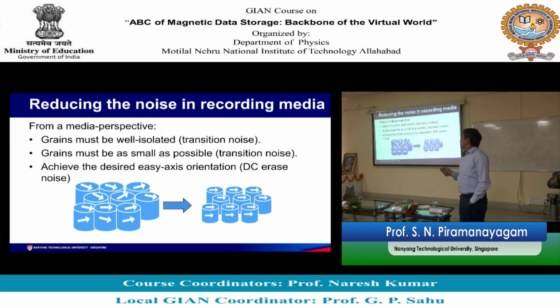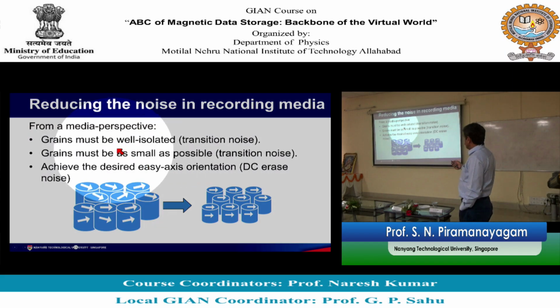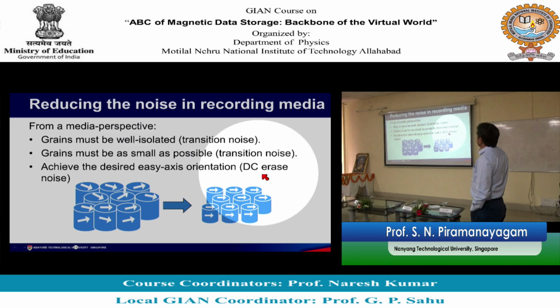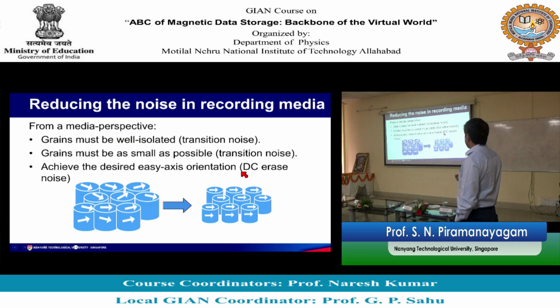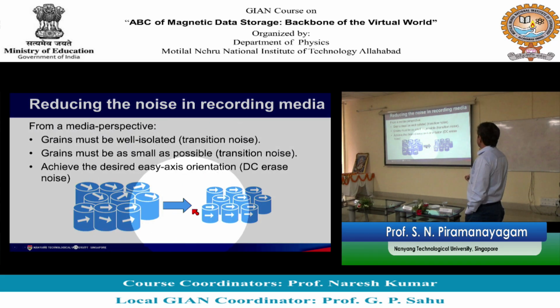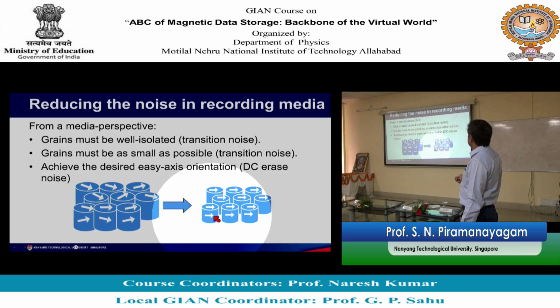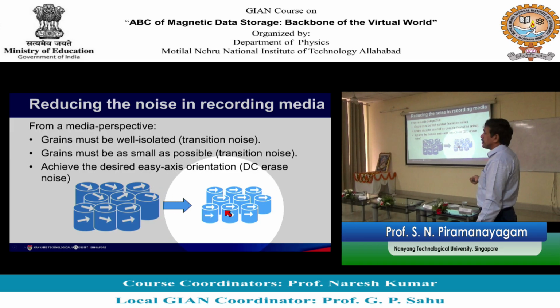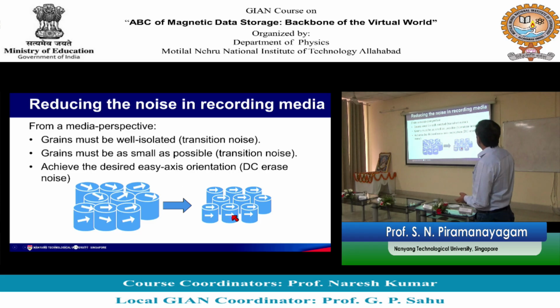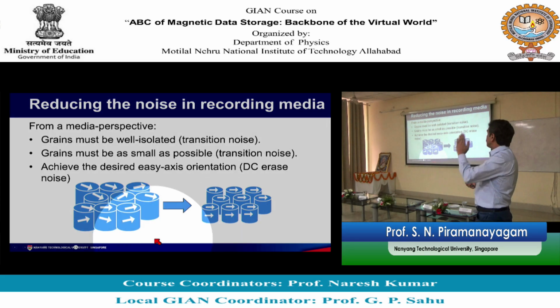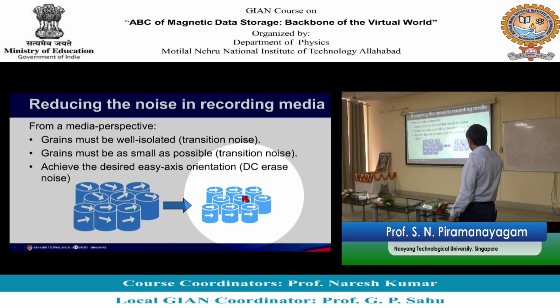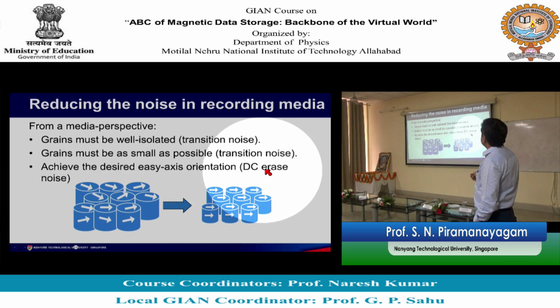Yesterday we learned that we want to reduce the noise, so we have to reduce the DC erase noise. To have the lowest DC erase noise, we have to maximize the in-plane magnetization when doing longitudinal magnetic recording. You don't want any tilt out of plane. And when you do perpendicular recording, you want the magnetization to be completely perpendicular, not having any tilt. That will help to reduce the DC erase noise.